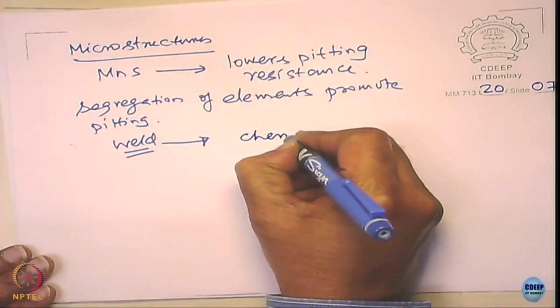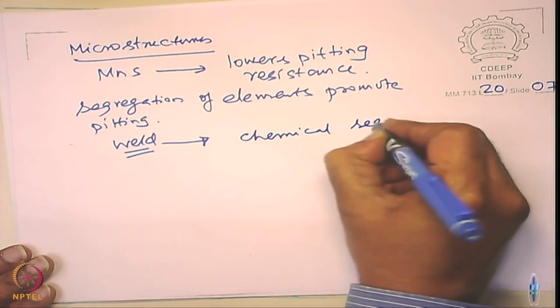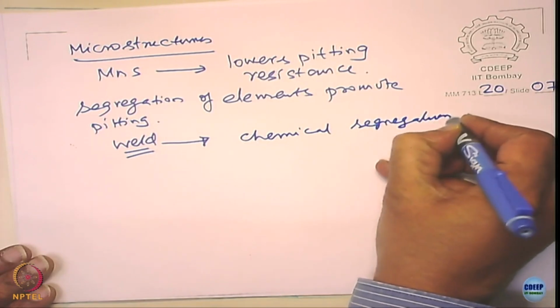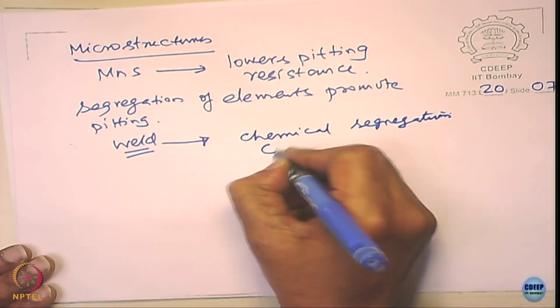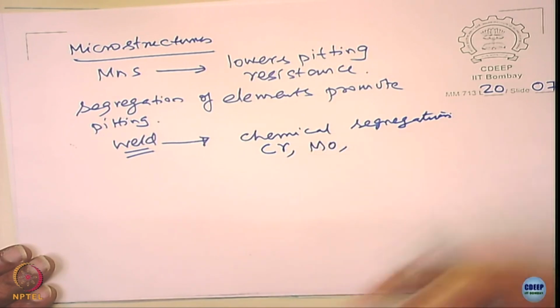Normally all your stainless steel, you have a molten liquid, pour it, and then they do hot rolling and then anneal it out, they make it chemically homogeneous. But when you weld it, you are going to have elements which segregate. Of course, we do not have time to discuss those issues. The welds will have chemical segregations, like segregation of chromium, molybdenum and things like that.